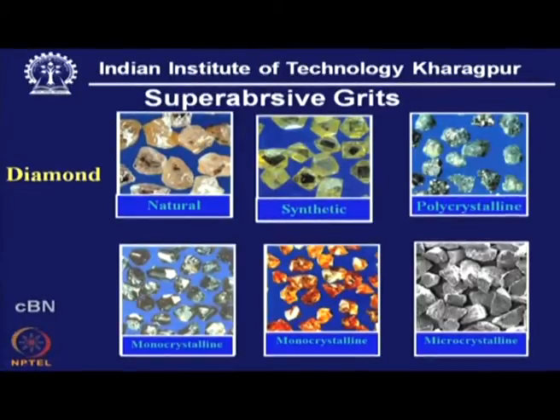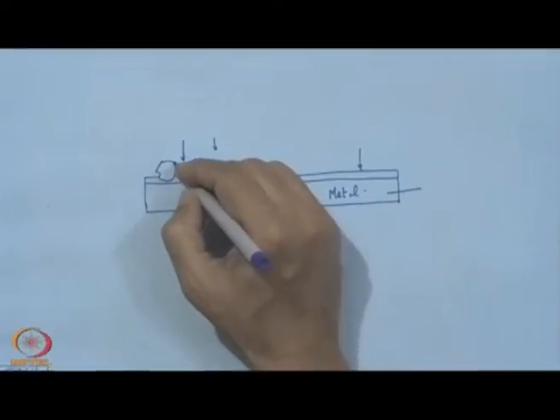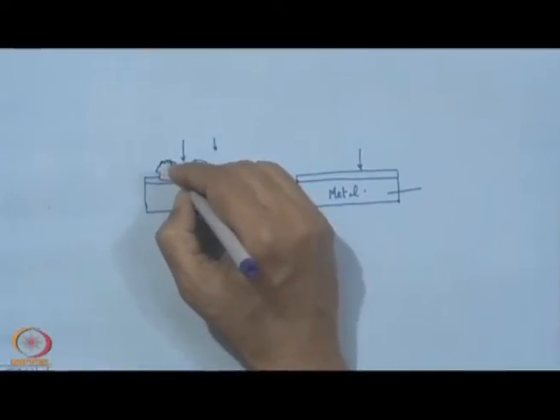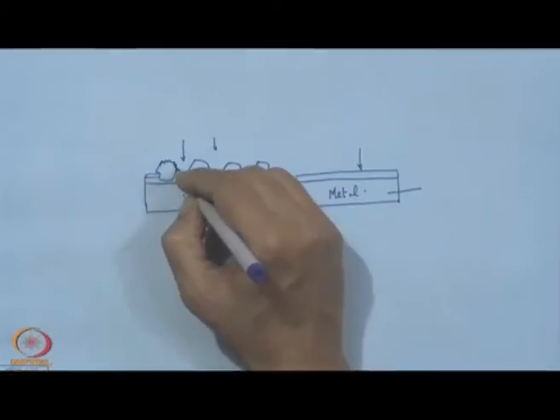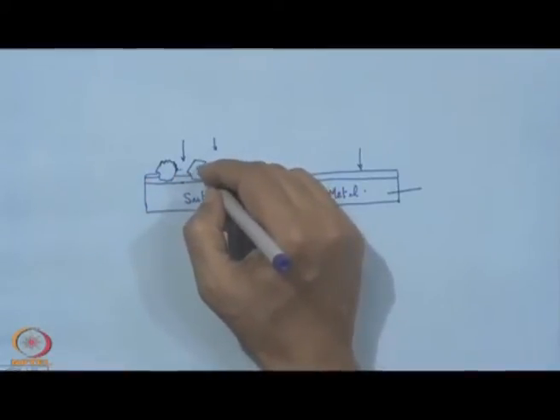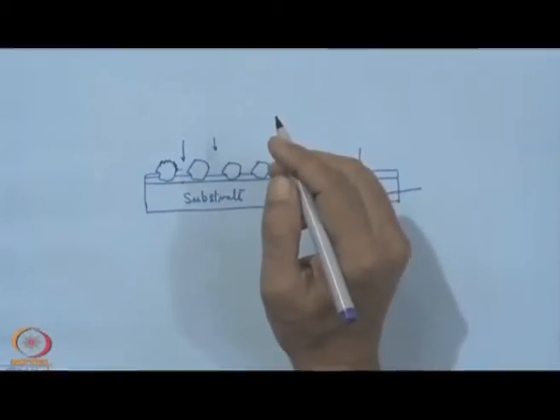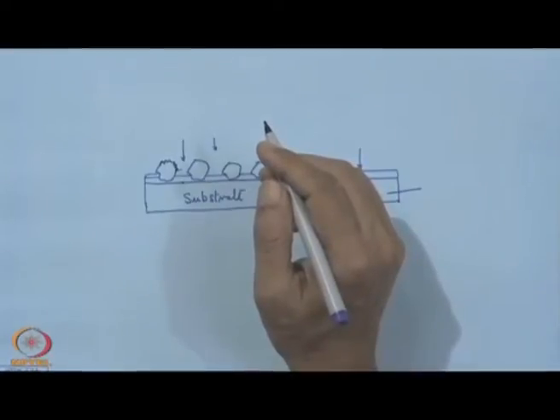By this, what we mean is that we have several cutting points already available on this grit, and at the same time this rough surface helps in anchorage of the grit. If we have this multifaceted surface, then this will help in anchorage of the grit in the bond. So, this is natural diamond.